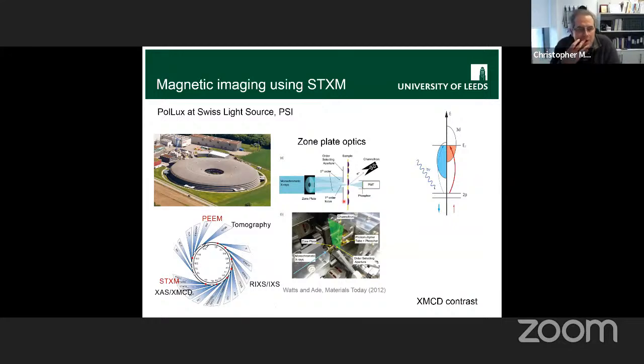Now, most of the rest of the results that I'm going to show you, we used scanning transmission X-ray microscopy at the Swiss Light Source, where there's a microscope about here in this storage ring in Villigen. And the way it works, here's a picture. Your sample goes in here, you shine X-rays through it. It has to be transparent to X-rays, so we make our samples on very thin membranes of silicon nitride that are maybe 100 or 200 nanometers thick. And there's a detector at the back that measures how much light you're shining through.